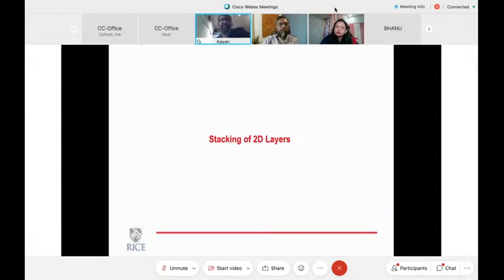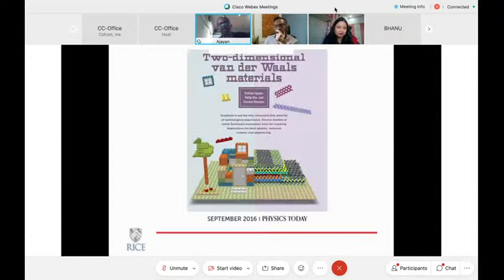Now let me come to something that is a little more exciting, in the sense that this is only applicable to these type of 2D material layers, and that has to do with stacking. Obviously, monolithic structures of layered materials exist as stacked layers of the same composition, but because you can now extract layers of different compositions, there is a possibility that you can mix and match and put them together as in a shuffled deck of cards, which makes it a very interesting approach, because these systems have never really existed before. So that's what I will talk about. People have imagined all kinds of architectures by simply stacking these 2D layers of different compositions and looking at what kind of properties this would have.